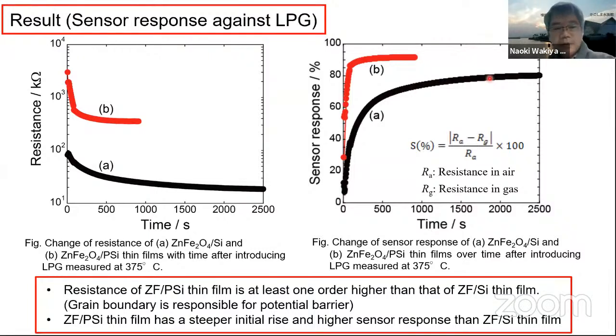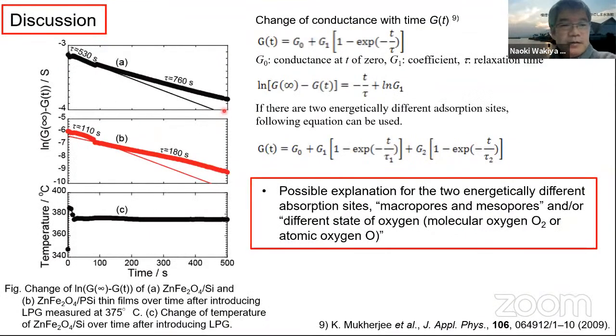And since there is some change of slope, we analyzed the change of this one. The change of the conductance with time is obtained like this. And this slide shows the slope change here. But this is a change of temperature. It means the temperature is constant, so this slope change is not derived from a temperature change during measurement.